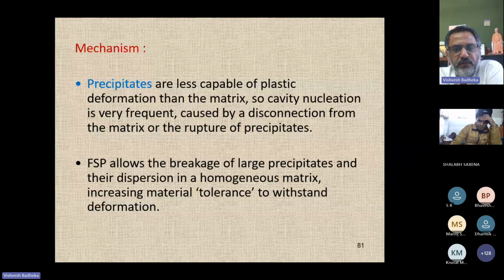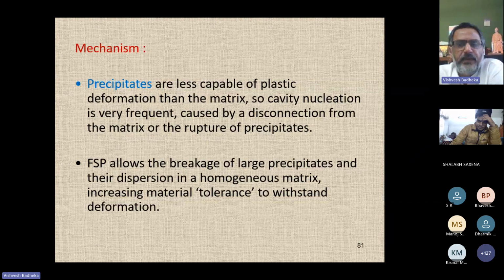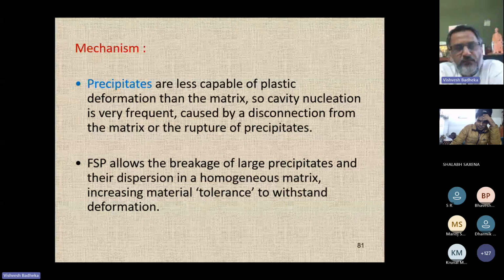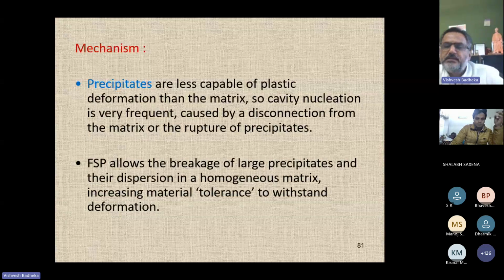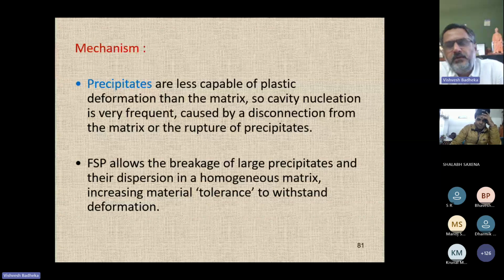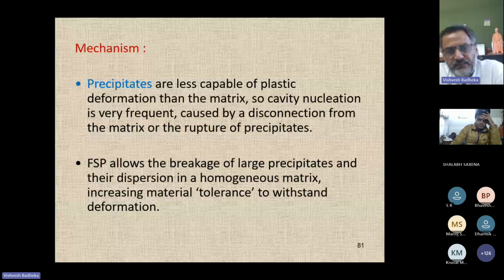The deformation behavior of the matrix is different, and the deformation behavior of the precipitate is different. So the chances are that you may get some cavities in the material, a disconnect from the matrix, or rupture of the precipitates. So FSP allows the breakage of large precipitates and their dispersion in a homogeneous matrix, and increases the material's tolerance to withstand the deformation. This is the crux of why FSP helps you improve the property.